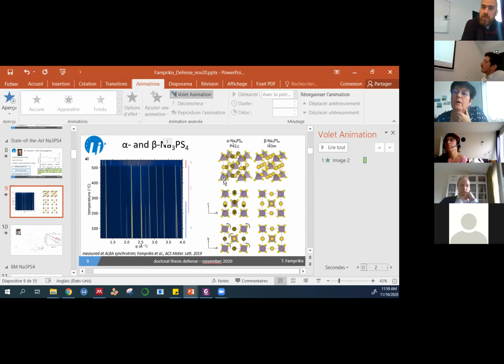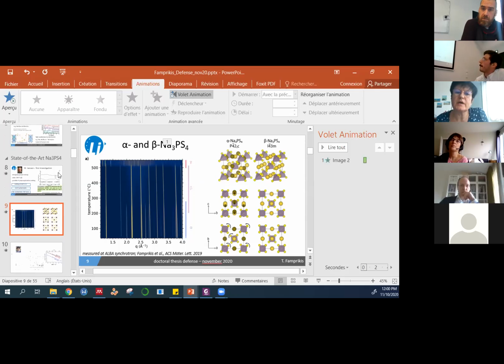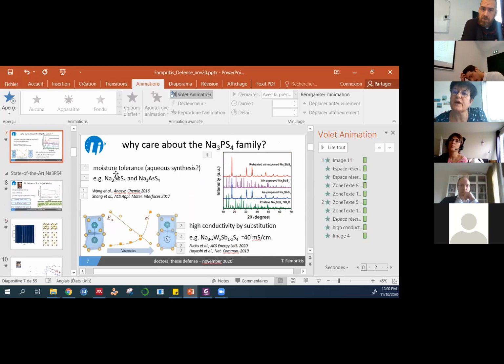If we have off-stoichiometry, my feeling would be that it would be on the opposite side than what I proposed for Li3PS4. That is indeed something that comes out from my studies on Li3PS4. Since I also work on Li3PS4, it might be applied here, but to my knowledge, there's no off-stoichiometry argument for Li3PS4 like this that has been discussed in the literature. Whenever the argument is made that the stoichiometry is changed, it is made in conjunction with something made on purpose, some structural substitution made on purpose, like the one I showed for tungsten. Right? And Theo, did you consider by theoretical calculation the possibility of defects in this material?